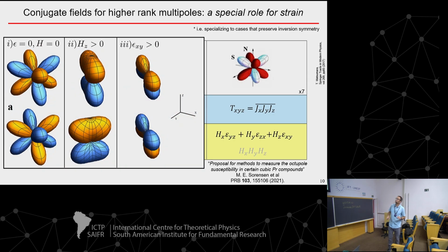So you can develop some physical intuition just by looking at the symmetries of these objects. So if I draw here, imagine a doublet state corresponding to octupole up and octupole down. So these are north and south poles, if you like. This is showing magnetization density. And I want to split that linearly. So if I were to apply a magnetic field and induce a dipole, I will strengthen the north poles in this direction or strengthen the north poles in this direction, but the magnetic field doesn't differentiate these states. Nevertheless, I've got charge density, which is sort of skewed around. And so now if I were to shear this, I will differentiate between these 2 states, right?